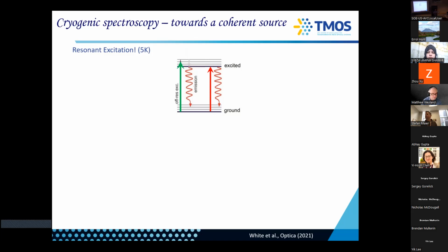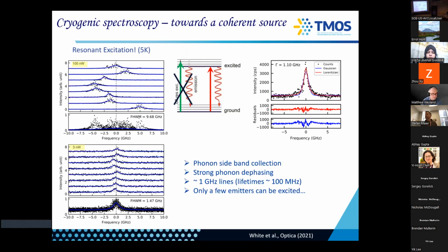You cannot really collect cross polarization yet. It's a bit more complicated, so we collect the phonons. And so what you see then is that the emitters, this is our best result. The emitters are about 1 gigahertz broad. If you compare it to the natural line width, they should be around 100 megahertz. So that's your lifetime of about 3 nanoseconds. So inverse of that should give you about 100 megahertz lines. So we are 10 times broader, not good.